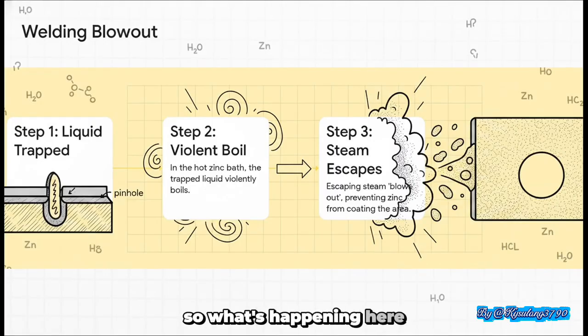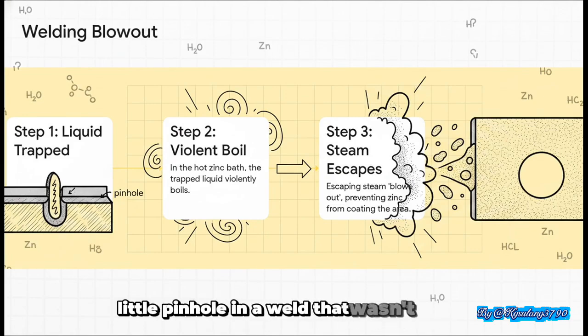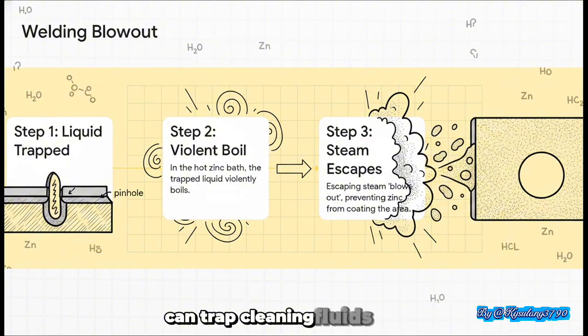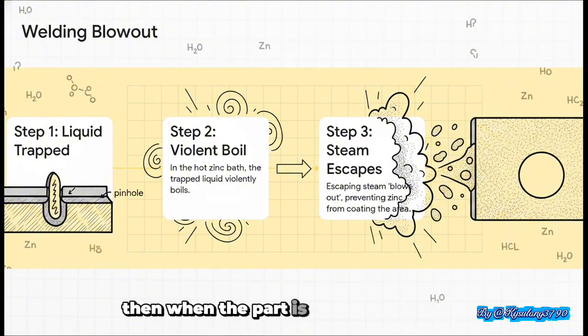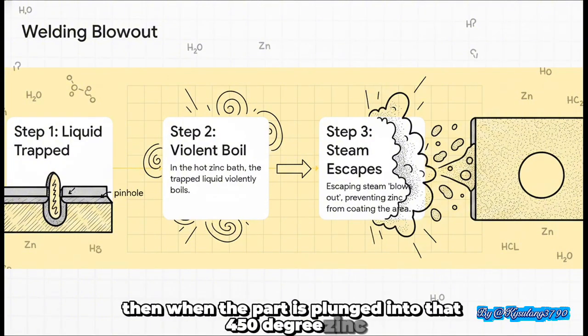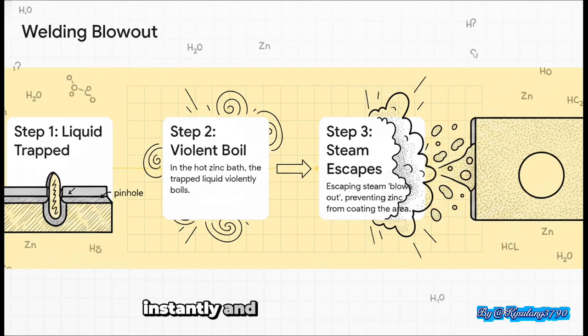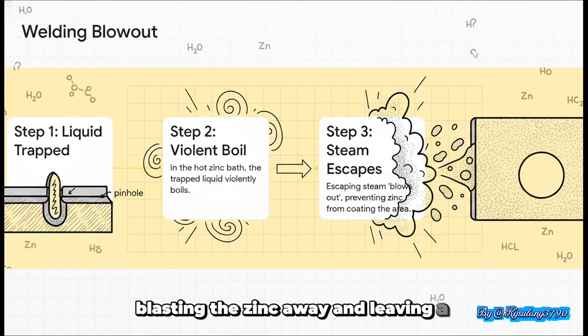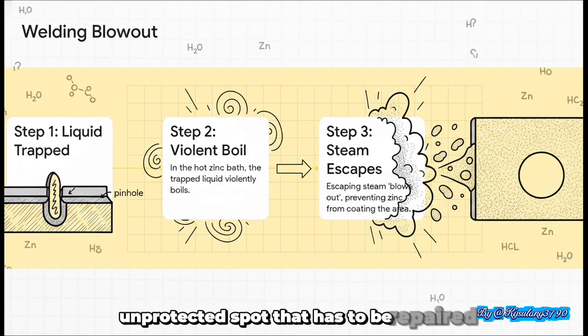So what's happening here is just some pretty intense physics. A tiny little pinhole in a weld that wasn't sealed properly can trap cleaning fluids inside. Then, when the part is plunged into that 450-degree zinc, the trapped liquid instantly and violently flashes into steam. That steam has to go somewhere, so it blows out, blasting the zinc away and leaving a bare, unprotected spot that has to be repaired.